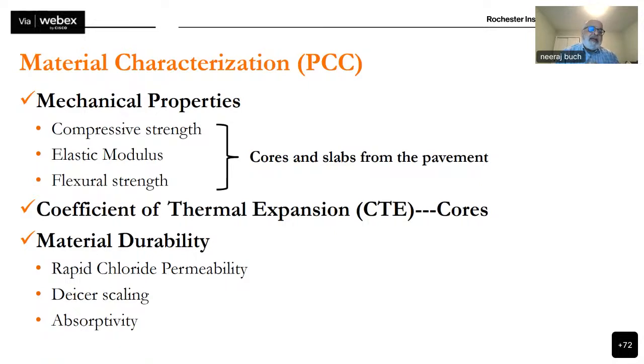And then, of course, we looked at some material properties. We looked at de-icer scaling. We looked at absorptivity of moisture, because the scaling and the absorption capacity of the concrete slab are important, especially in freeze-thaw zones. And then, of course, we looked at the resistivity, which is really a measure of permeability of the concrete, because again, when you construct pavements in freeze-thaw conditions, in winter, salt is put on the pavements to minimize the icing of the pavement, and you want to make sure that the chlorides in the salt do not permeate into the concrete and cause material-related durability problems.